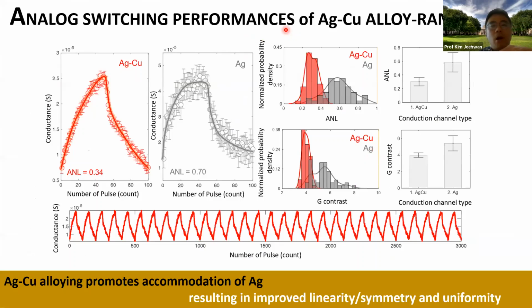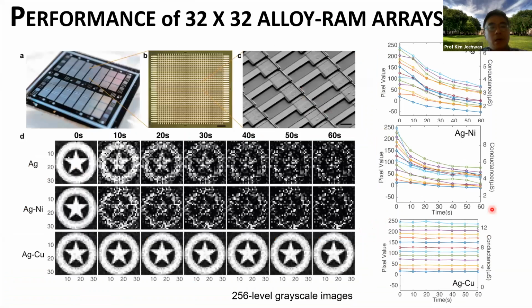Silver copper alloyed RAM also shows excellent analog switching behavior. As you can see here, silver copper shows linear and symmetrical behavior compared to the pure silver device, which is crucial for excellent analog neuromorphic computing. The silver copper device repeatedly shows symmetrical potentiation and depression behavior. With this, we were so encouraged to make arrays, which are 32 by 32 sized arrays.